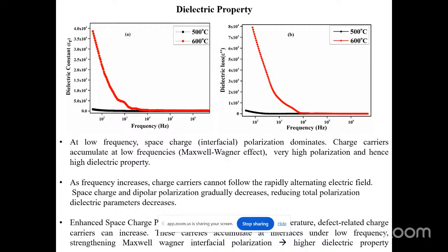Now, dielectric properties. The dielectric constant is very high at low frequencies because of space charge or interfacial polarization, also known as the Maxwell-Wagner effect. At low frequency, charge carriers accumulate at grain boundaries, producing strong polarization. As the frequency increases, these charge carriers cannot follow the rapidly changing electric field. Therefore, polarization decreases and the dielectric constant gradually reduces.